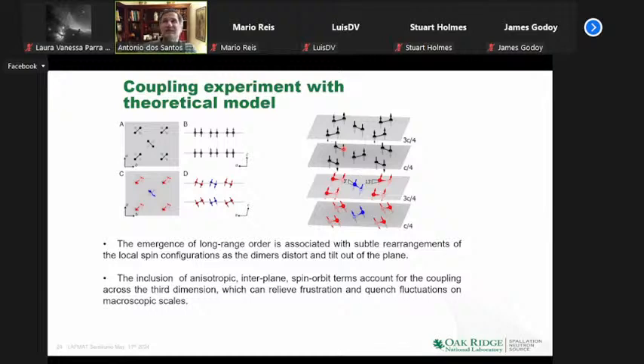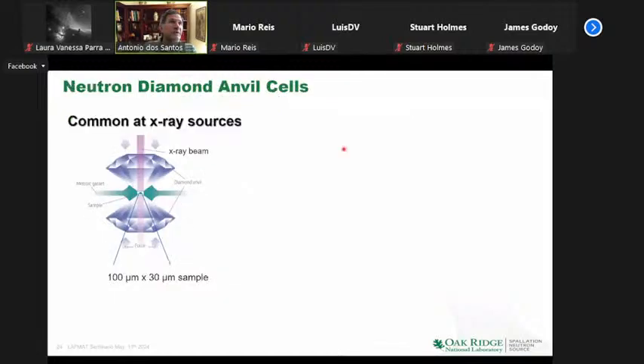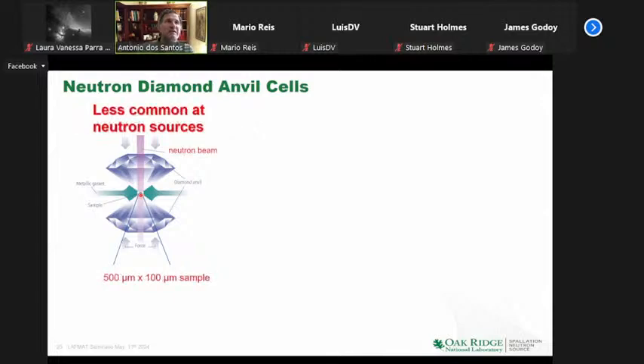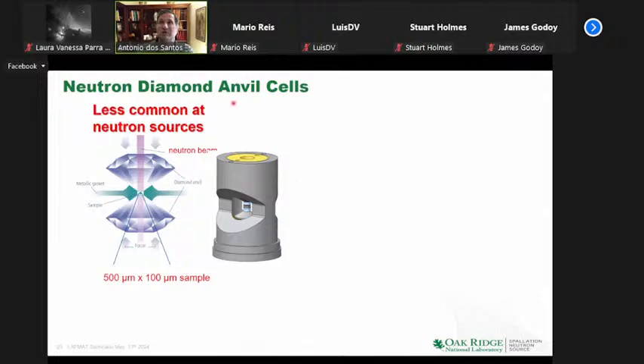The next cell is going to be an illustration of the challenges of using ultra high pressures. Some of us are familiar with the X-ray diamond anvil cells. Samples are about 100 microns by 30 microns thick, and these are common at X-ray sources. But these are much less common at neutron sources because to see anything, you need to increase the sample size by a great amount. We have developed that at Oak Ridge, and this is what a pressure cell looks like.